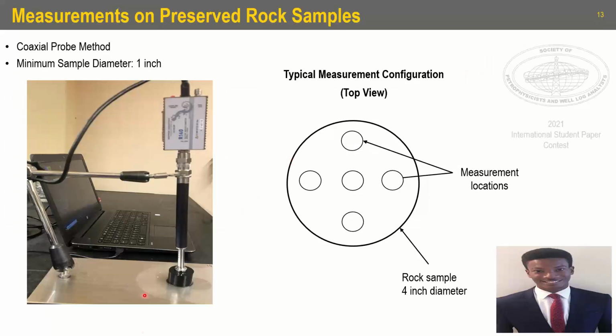Still using this same method, we show here how the preserved rock sample is placed directly under the probe. And then we show here the typical measurement configuration, showing the various measurement locations that we can measure on the sample. The minimum sample diameter for this method is 1 inch, and we can use up to as high as 4-inch sample diameter.